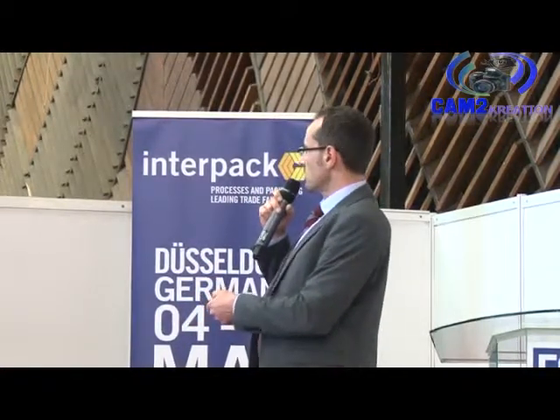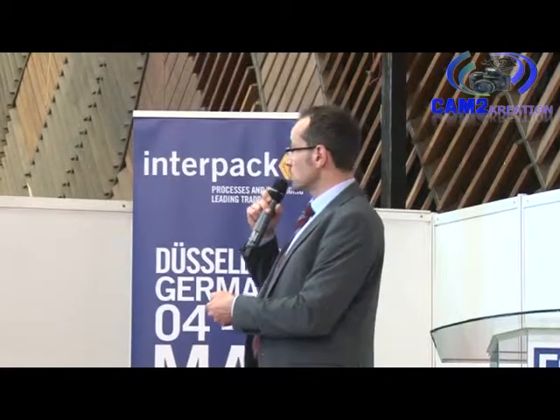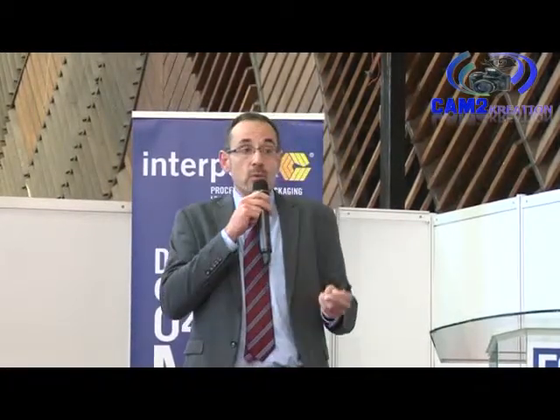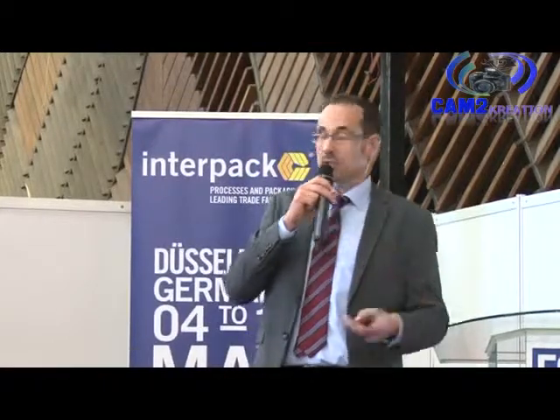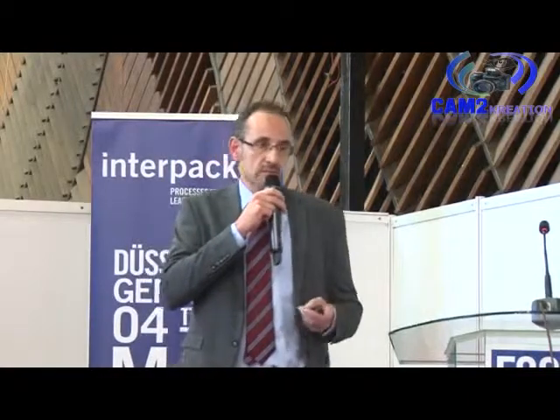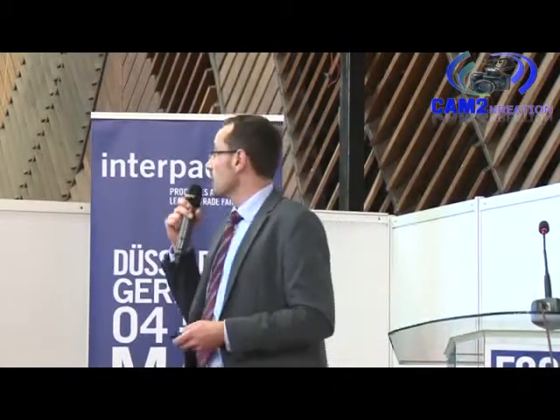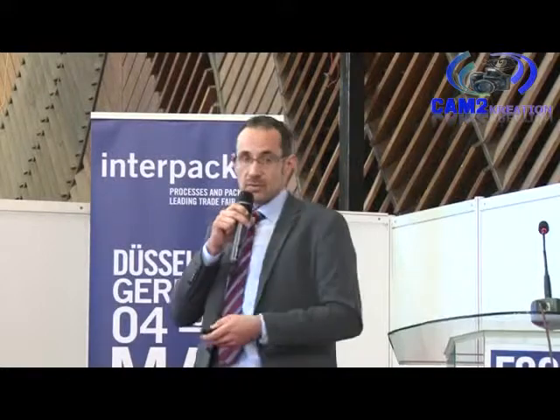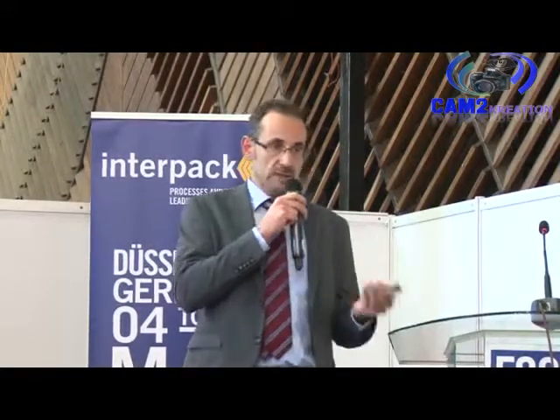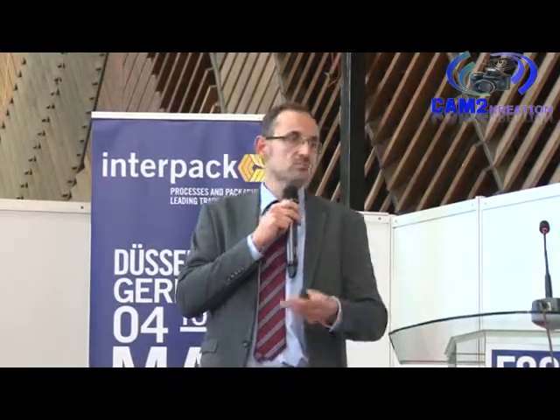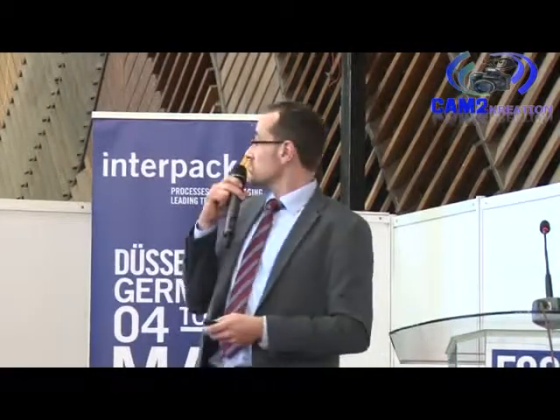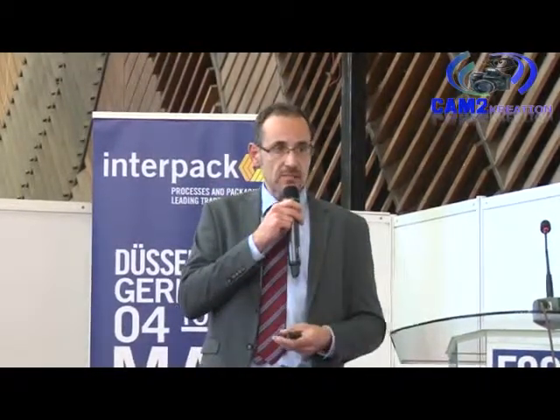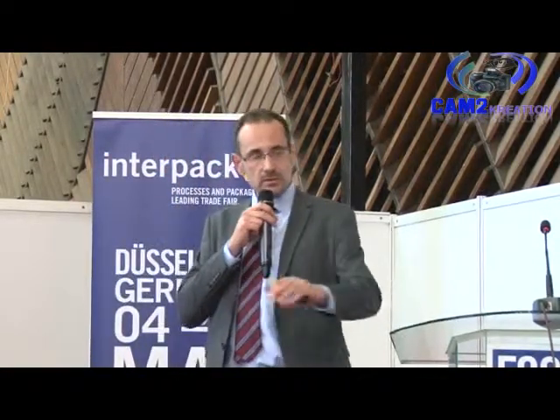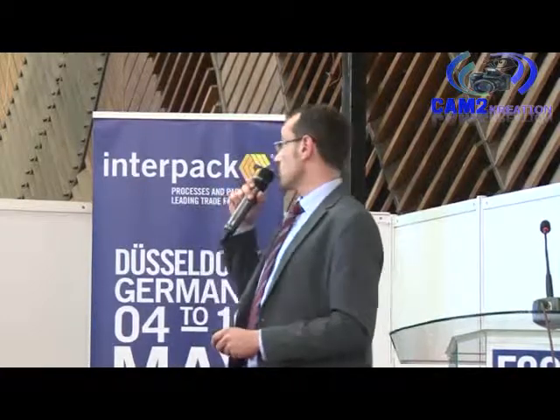This cast film technology is used for nylon. It can go from only one layer, which is then a film for lamination, up to 11 layers or even more. This technology is available nowadays. So it can be used directly as a co-extruded film: you just make cast film, you make a pouch, and the package is ready. If this is not enough, if you need printing, for example, or other properties, you take a monolayer cast film and you can use it for lamination, for thermoforming, for example.